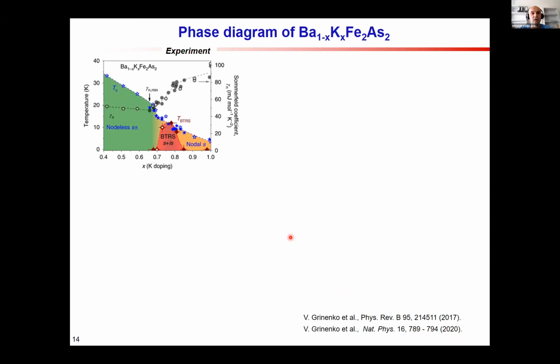So finally, I would like to summarize our findings and present the phase diagram. This is the temperature-doping phase diagram, and the blue stars are the superconducting critical temperature. The superconducting critical temperature decreases with doping above the optimal doping. So optimal doping is somewhere here. It goes down nearly linearly, and then abruptly changes around 60–70% of the doping and flattens, and in this range we observed the time reversal symmetry breaking state.